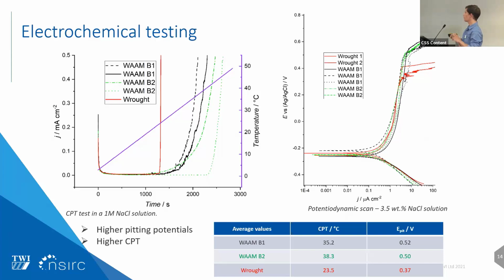On the other hand, for the wrought, you can clearly see that it is well below the value we have for the two WAAM grades. In the literature, the CPT for wrought 316L would be between 19 and maybe 24 degrees. So it is below what we have by about 10 degrees Celsius. We can say with confidence that we have a different behavior here.